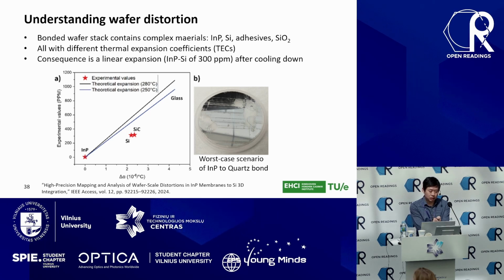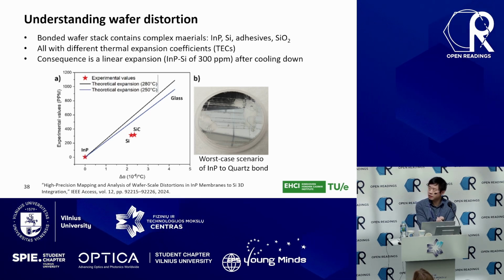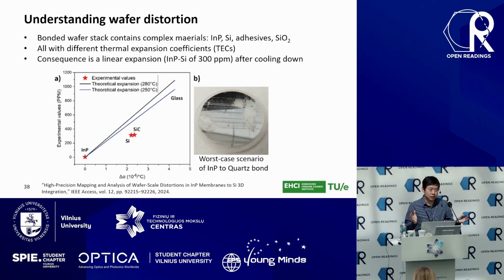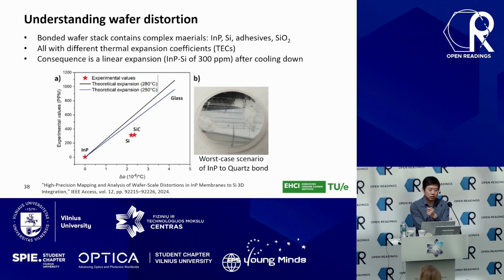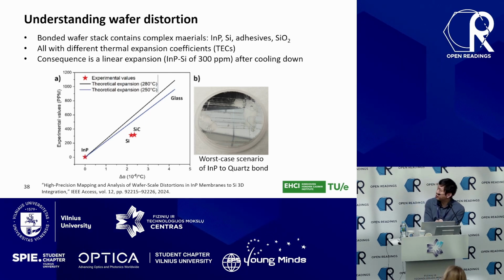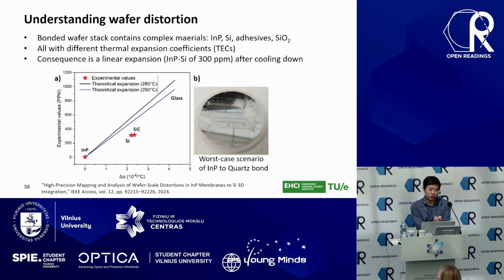So that leads to the plot on the right. You see the data for indium phosphide. Of course, this is an indium phosphide to indium phosphide bond, the same coefficient, right? So you don't expect the expansion or the strain built inside your system, but you do see a significant value around 300 ppm for silicon and for silicon carbide as a substrate.